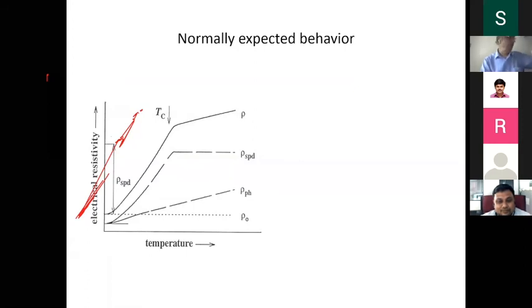My time is up, but I'll take a few minutes to show that even the so-called normal rare earths, which people traditionally believed to be normal, also show anomaly. In fact, that work has come out from our own group. We were the first to point out, studying normal rare earth materials, that sometimes they behave like abnormal materials, as if 4f electrons are delocalized. But in reality, 4f electrons are not delocalized. They remain localized, but they look like delocalized. It's a very funny phenomenon. A new concept is evolving. There are papers in PRL recently, I will show you that. A new magnetism concept has evolved. So I just want to tell you.